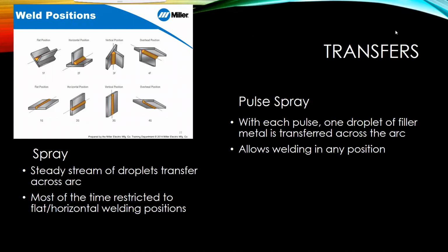So, talking a little bit about transfers. We've talked in the past about multiple transfers, like short circuit and a little bit on globular. We've also talked about spray and pulse spray. When we're welding with aluminum, there are two main ones that we're going to be focusing on. I want to touch on spray transfer just because it's the original, the history is there. With spray transfer, you have a steady stream of droplets that transfer across the arc. But one of the issues is that it can be restricted to flat and horizontal welding positions. Also, it puts a lot of heat into the plate.